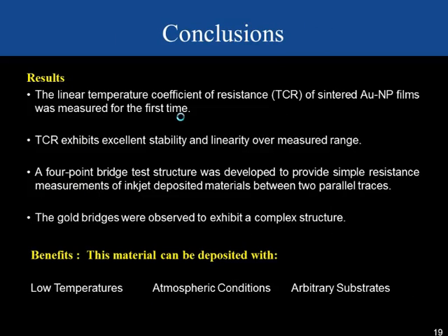So with that, I'd like to thank you for your attention, and I've shown you the first measurement results of sintered gold nanoparticle films and their TCRs, and they exhibited high stability and linearity over the measured range. A 4-point test structure was introduced and used for our experiments, and is hopefully useful for other inkjet explorations. Also, our bridges were observed to have a complex structure, which may potentially offer several interesting sensing applications where a high surface area of gold is desirable. One thing to remember about this technology is that we can deposit gold at low temperatures in atmospheric conditions on arbitrary substrates, which offers interesting applications over conventional techniques.